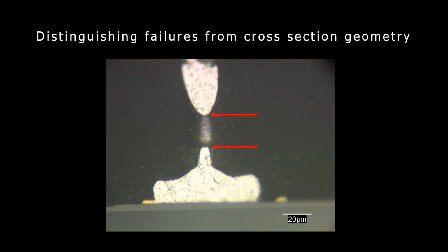Here we see a cross-section of a wire bond failure. The top shape is conical due to the bond wire being distorted out of the plane of the cross-section. When we see this conical shape, this means that this is not a failure. The bottom shape is more square. This indicates that the failure occurred here.